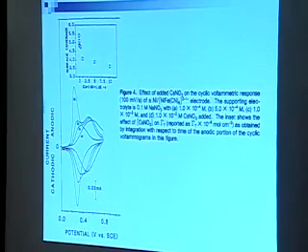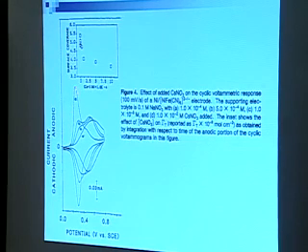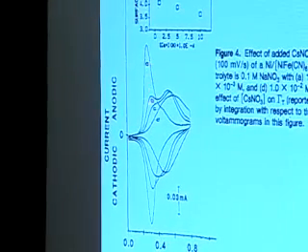So how are we going to do this? We're going to run cyclic voltammograms in the media that has the cells, because the cesium that's in the cell stays in the cell, and we can't detect it. When the cell lyses, it comes out, and we detect it. The media has lots of salt and things in it to make the cells happy, so we have plenty of supporting electrolyte and water and whatnot. The idea was: here is your electrode in primarily sodium ions, sodium nitrate, and just a few cesium ions around. Then you add more cesium ions, and you see the sodium peak go down and the cesium wave go up.